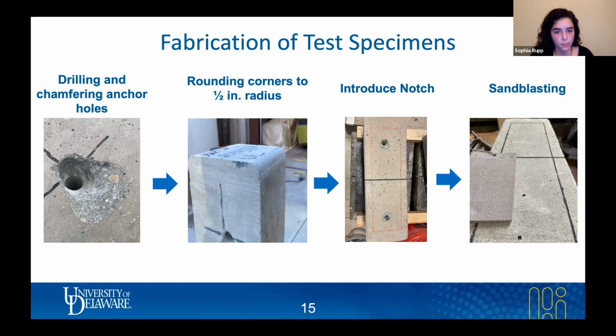And the reason for that is because we also apply what is known as shear wraps around the sides. And that's just to ensure that the beam will fail in flexure rather than shear. As I mentioned, we introduced that notch in the center line. And then finally, you sandblast the surface of the beam to give it a surface roughness so that there's good bond between the CFRP that's being applied and the concrete.